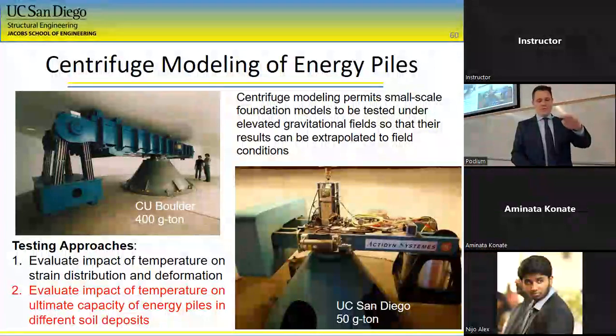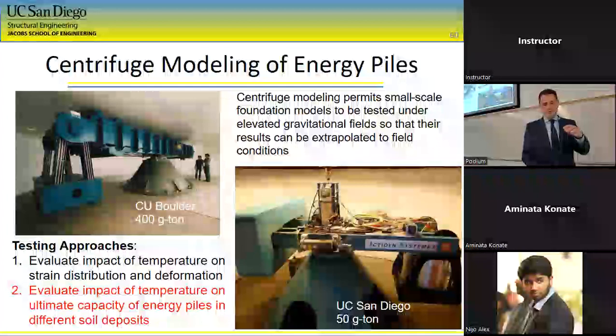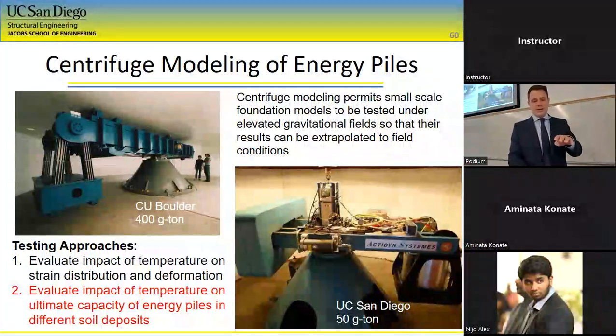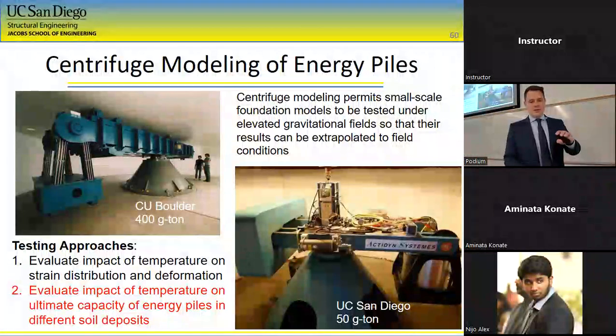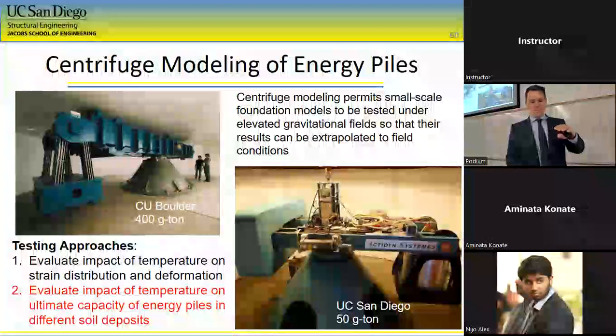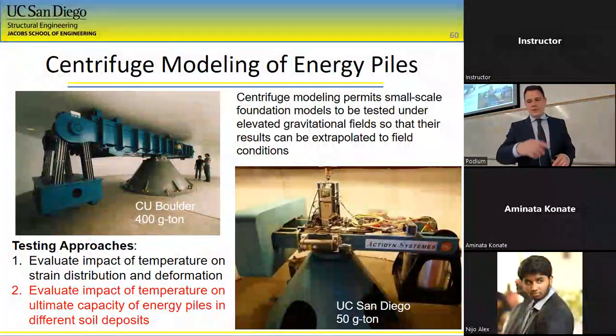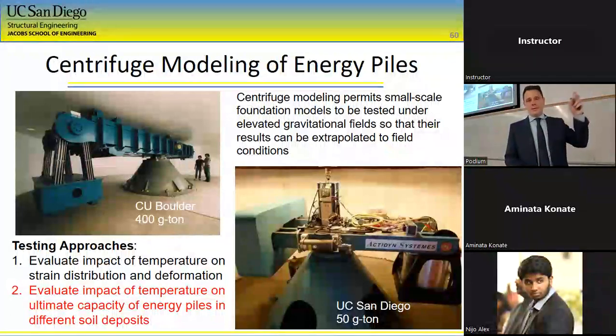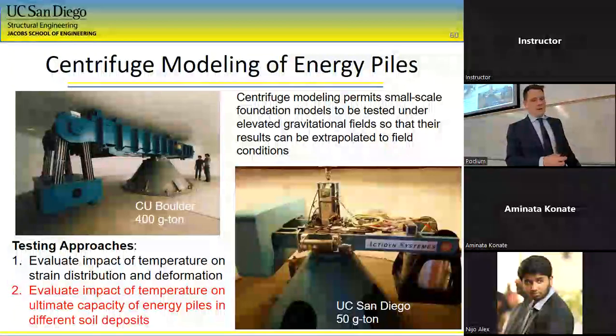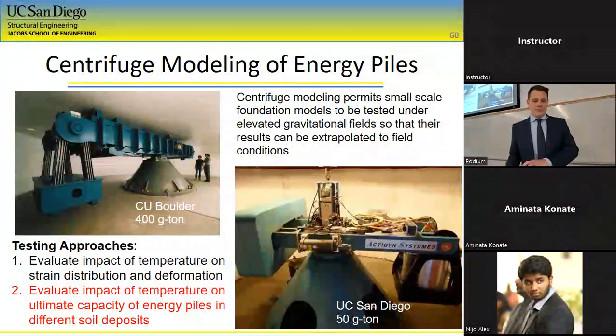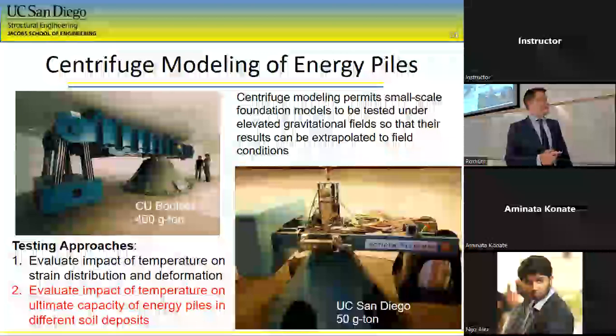So if we have a sand layer and we spin it in the centrifuge, you're going to increase the gravitational forces on that sand layer. So the stresses are going to increase, and you can use some scaling relationships that if you spin something at 50 Gs, for example, it's going to represent a sand layer that is 50 times bigger. So we can do tests in the centrifuge and then extrapolate those to the field.